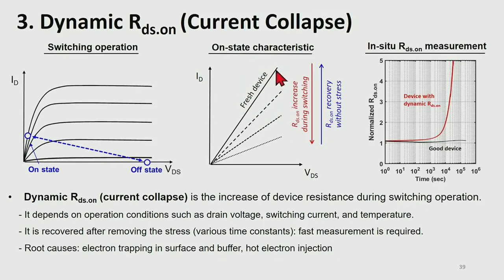But this degradation is not permanent. If you stop switching and wait for enough time, most of the RDS,on degradation can be recovered. The recovery time varies from some microseconds to a few tens of hours. So to capture all the dynamic RDS,on effect, it is important to minimize the delay between the stress and measurement. So this right figure shows the dynamic RDS,on of good and bad devices under high voltage switching, and the RDS,on was measured with less than 1 microsecond delay.